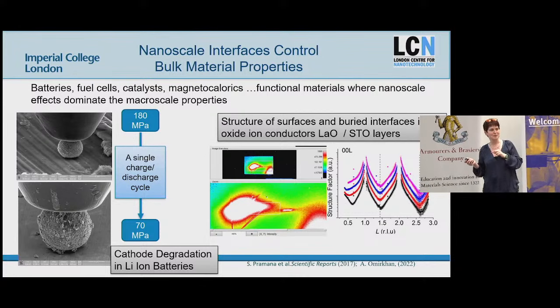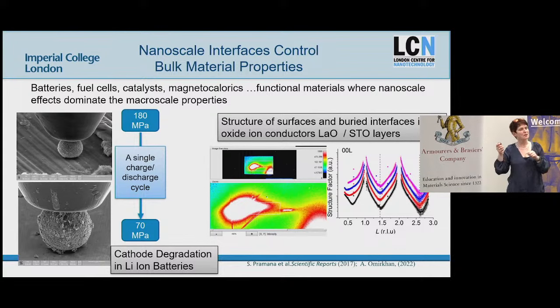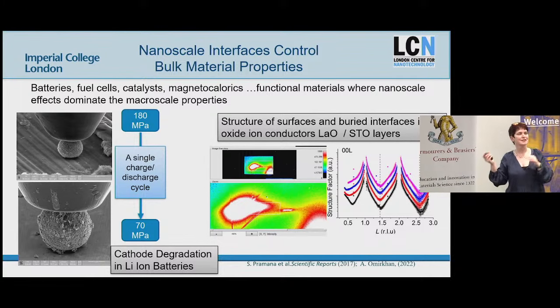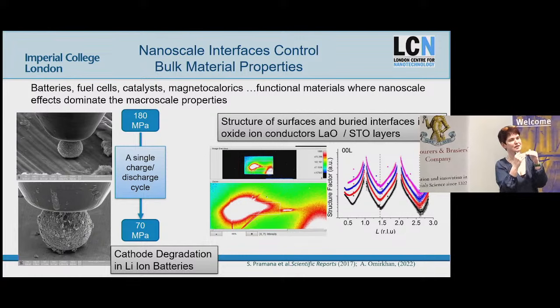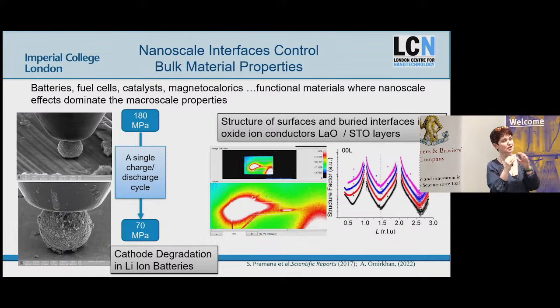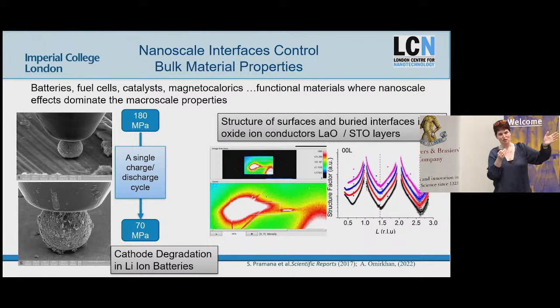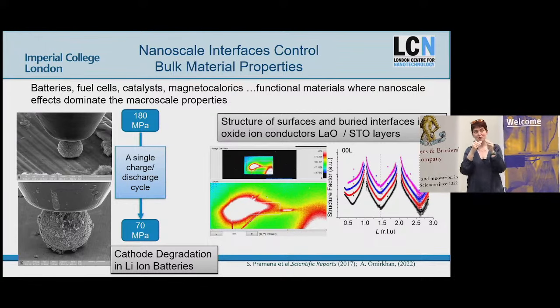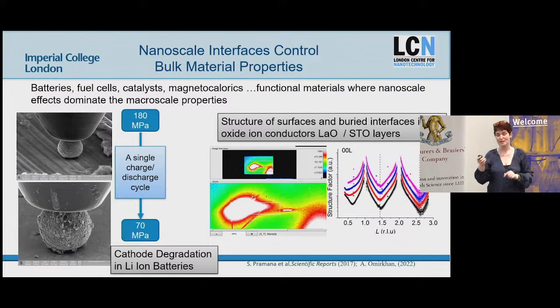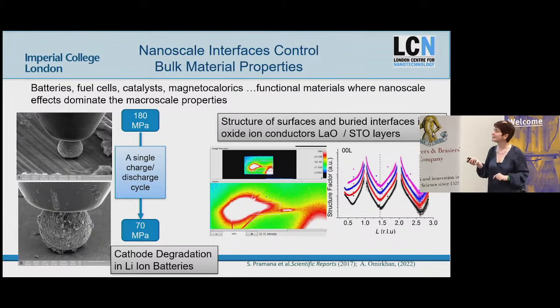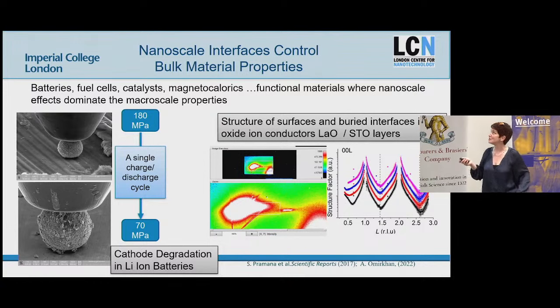These are very hard experiments to do, and they take a long time to set up, and you need a synchrotron, right? But this is the right experiment to do to try and understand what's in a buried interface in situ. Right? You can't do that experiment if you take it off and slice it and put it in an electron microscope. You can't get that from a functional measurement. You've got to find the right measurement, and if there's not a right measurement, you have to go make one, right? I think that's the message we should take away.